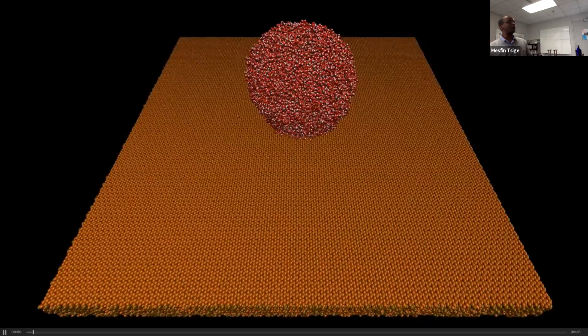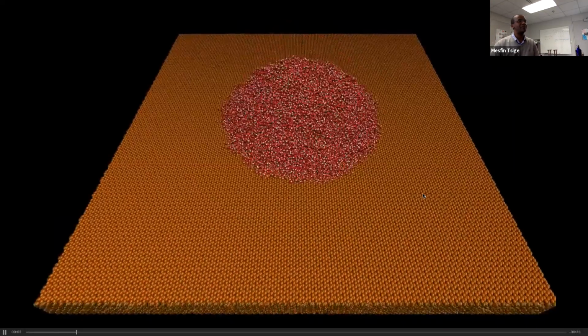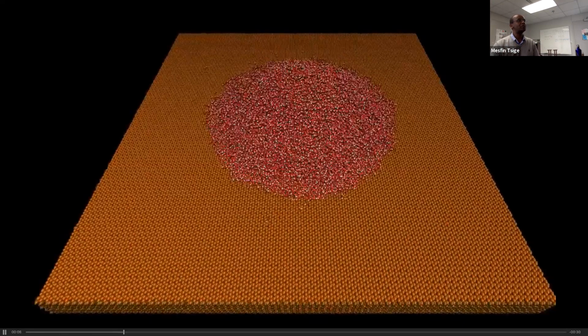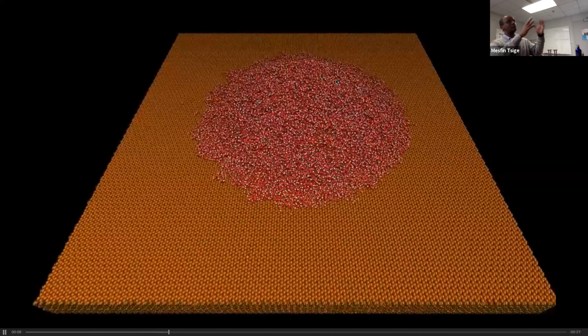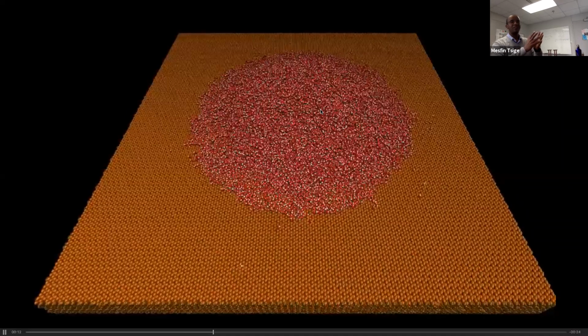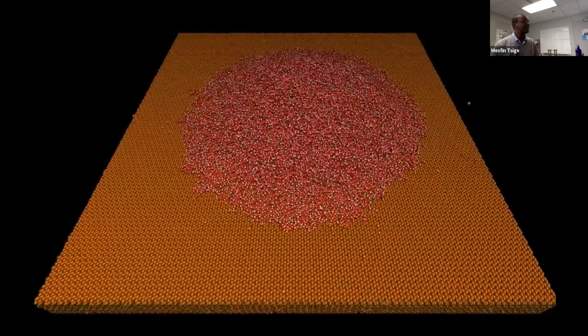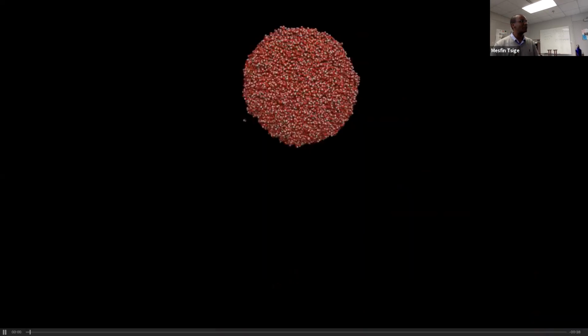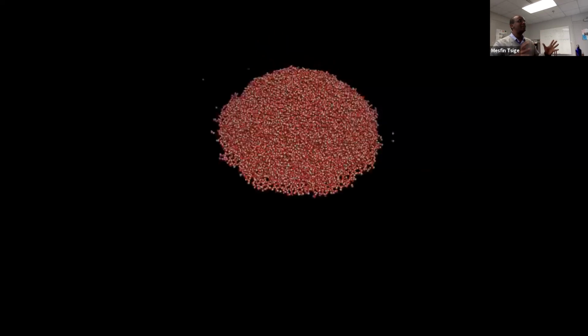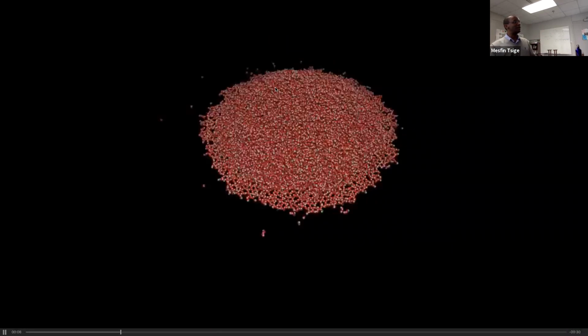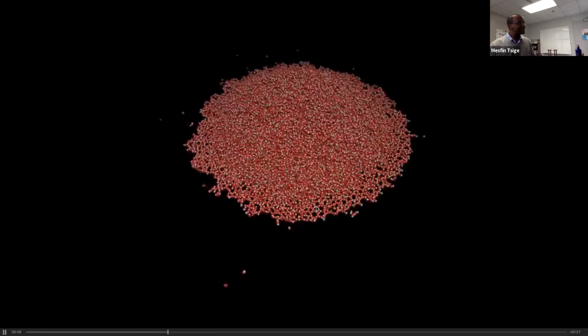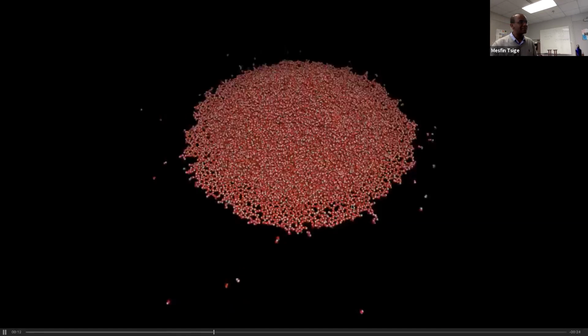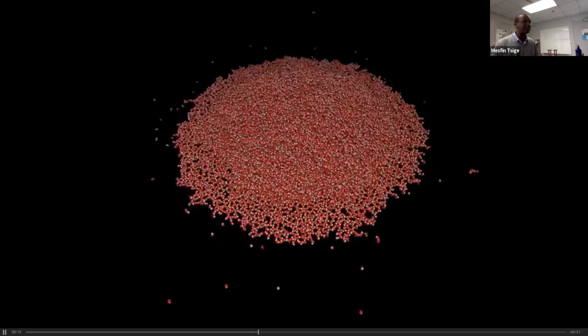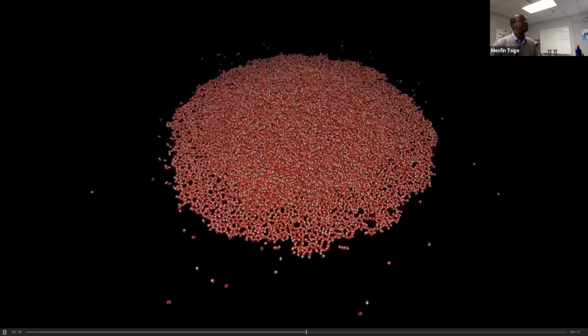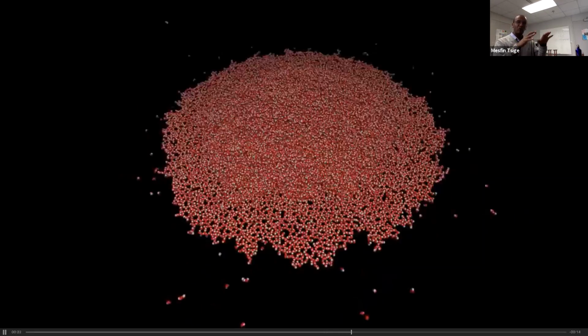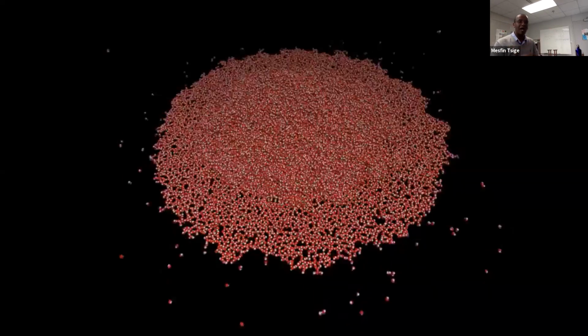When we put a water droplet on the sapphire surface, I'm not showing you the OH groups, to avoid confusion with the spreading water. When we bring this water onto the surface, it is actually spreading. If I hide the substrate, you can probably see it more clearly. This water droplet is coming, and then you have a single monolayer coming out, and on top of that we have a hemispherical cap. So we have two different kinds of dynamics going on at the same time.